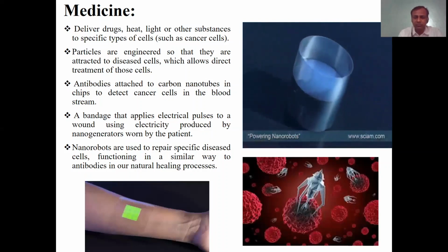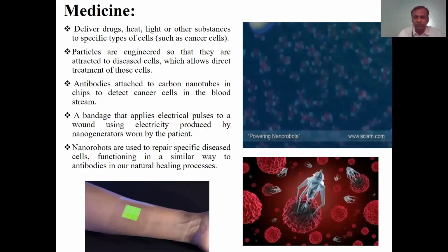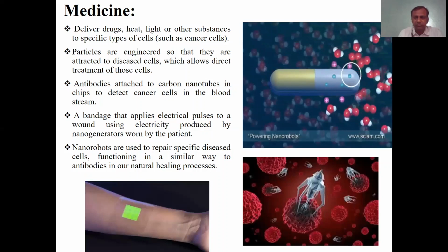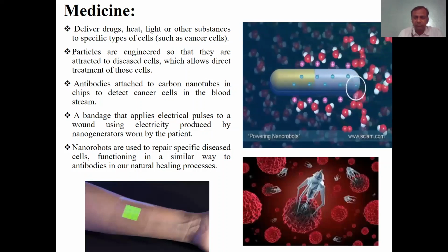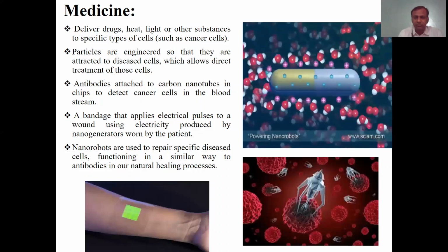This experiment uses a solution of water and hydrogen peroxide. A 1 micron long rod is inserted. One end is coated in platinum, the other in gold. The platinum surface catalyzes hydrogen peroxide molecules, stripping out electrons and protons and leaving oxygen.